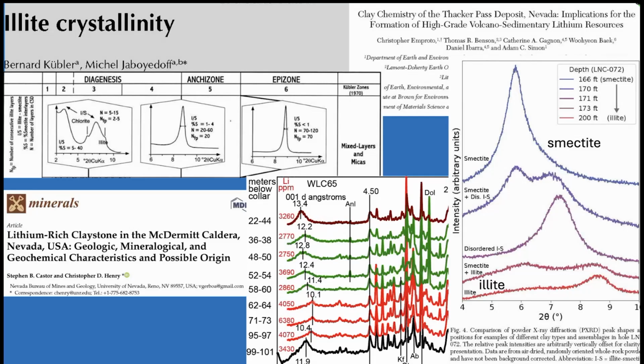the vertical plot here. This is a smectite peak. This is an illite peak. And we didn't do it the exact way that would be required to do the illite crystallinity. Nevertheless, what we see are very broad peaks. And this is another recent publication, again, on Thacker Pass. And they looked at a section here where this is a smectite peak, and then it's a transition downward into illite. And you can see all of these are very broad peaks. So qualitatively, it certainly doesn't suggest that illite is high temperature, but it's a little equivocal as to what exactly it means.